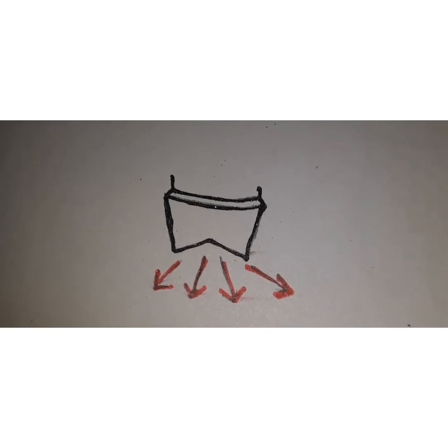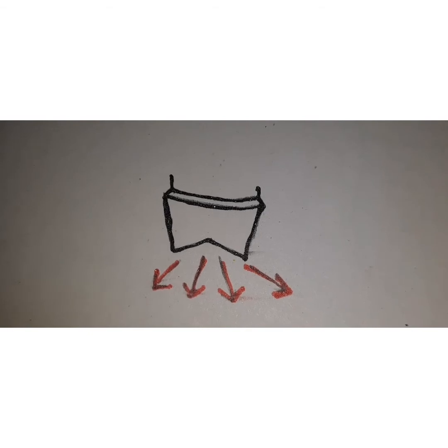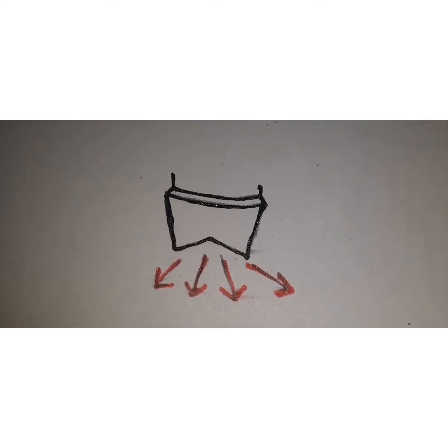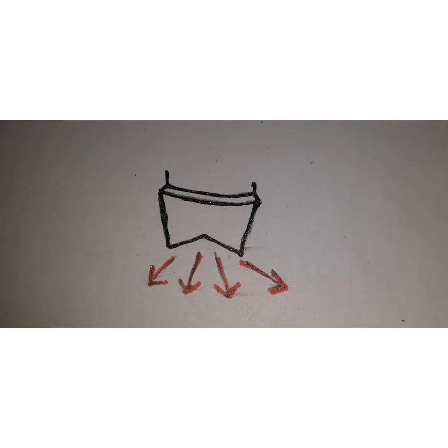It should not be that you are inserting and cementing the crown once the working stage of that cement has passed, and then you are trying to fit that. So definitely the crown is going to come out. There will be cementation failure of your restoration. So all these things you have to keep in mind so as to avoid cementation failure.